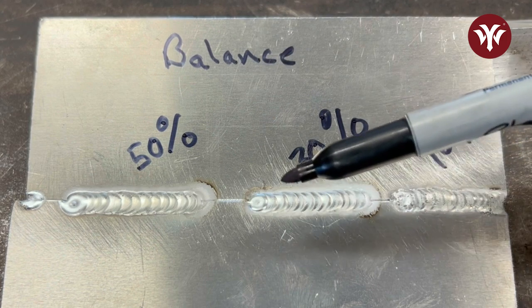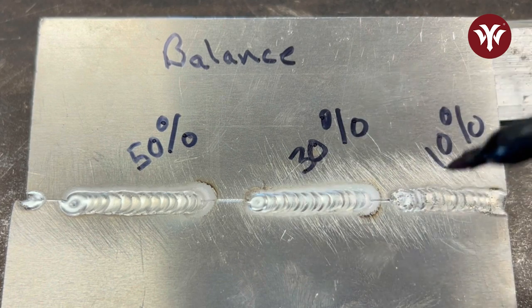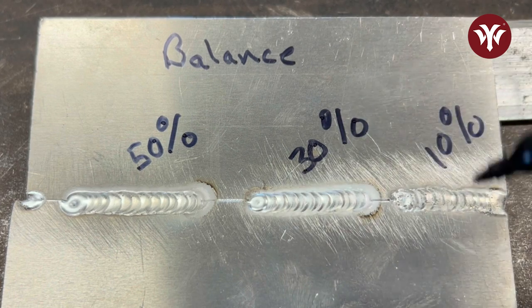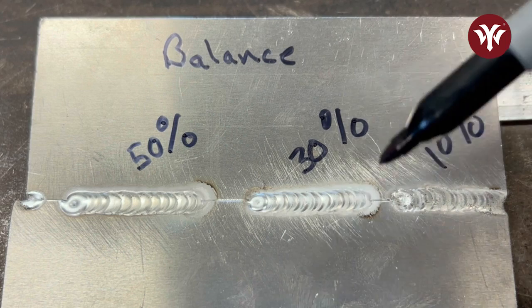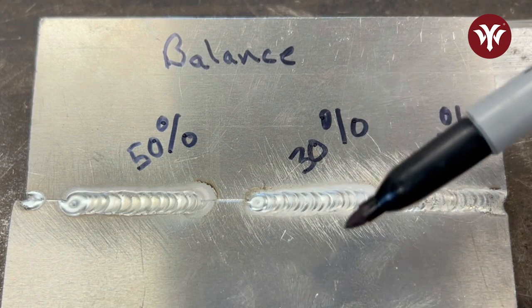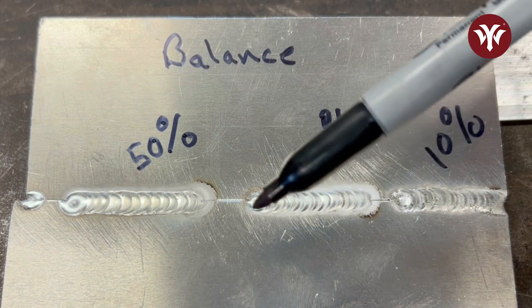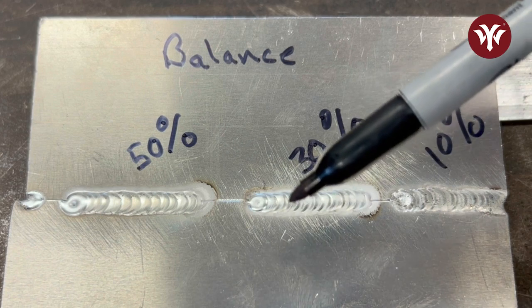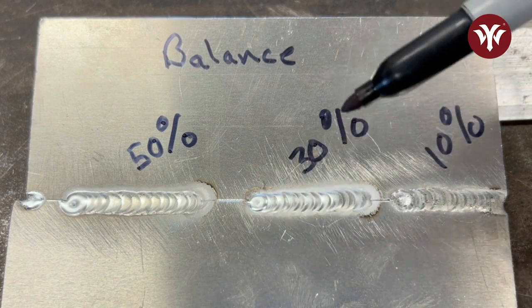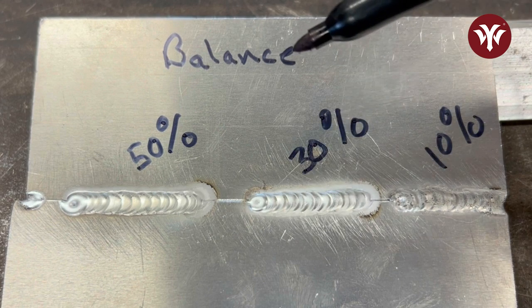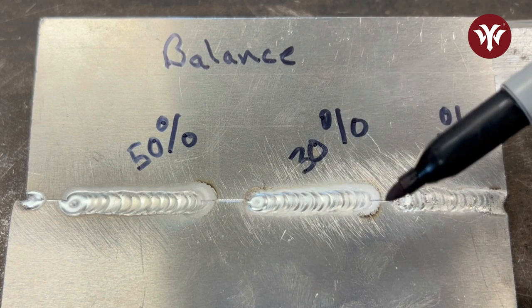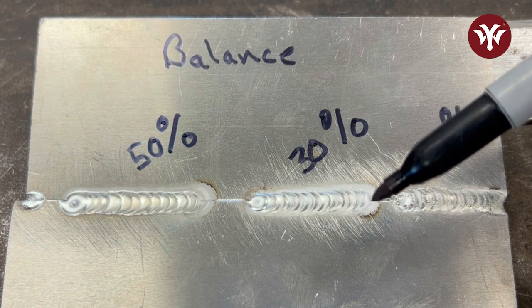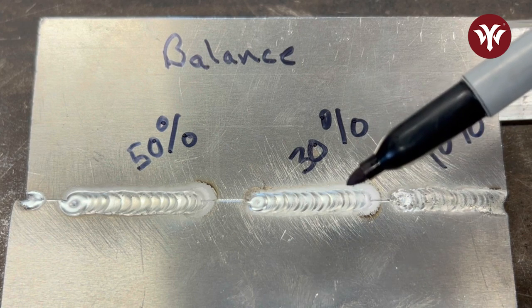I have more cleaning action to the top, which could be related to my torch angle. I probably should have my torch tipped towards myself a little bit more, which would have brought the arc and the cleaning action to the bottom, but it is still there and I'm happy with that. 30% is a nice, no pun intended, balance between putting heat into the part and getting enough required cleaning.